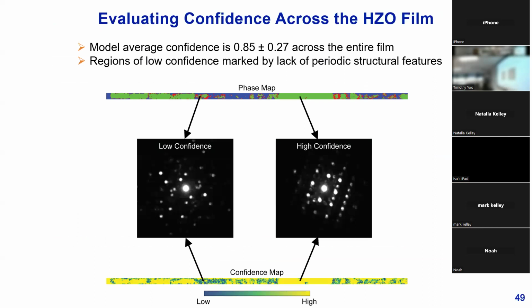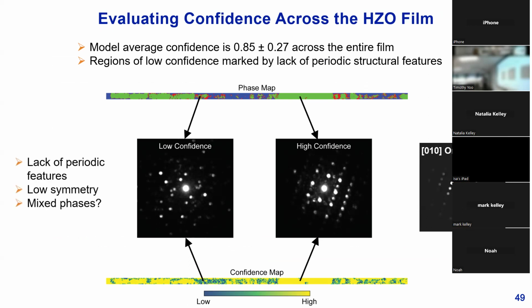And so taking a closer look at what's actually going on here, if we take a single pattern from one of these high confidence grains, we can see that indeed we see a nice low index zone axis pattern that can be quickly matched to simulations. In this case, again, we see that O1 orthorhombic. However, in the low confidence regions, we can see that we get this pattern that's overall not really giving us a lot to go off of, right? This lack of periodic features and symmetry would normally help us to identify diffraction patterns. And there's also a strong possibility that this is actually a result of mixed phases, which of course the model has not been trained on to identify, right?